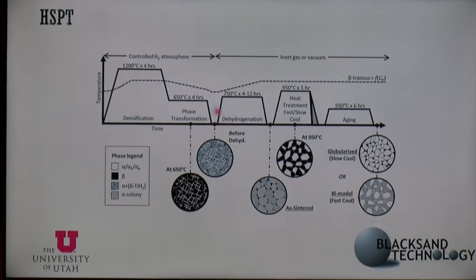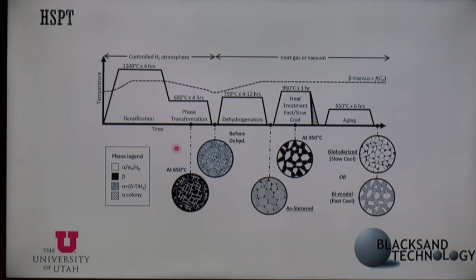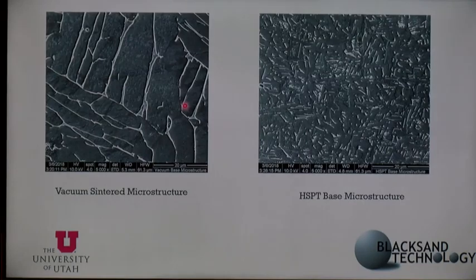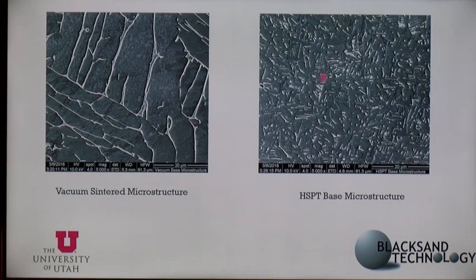You can see here that the left is the vacuum-sintered microstructure. This would be similar to what we would have at this point right here. So directly after this point, if we just completely stopped and didn't do anything with it, this would be a vacuum-sintered microstructure. By using that temperature, we control the grain size to go a lot smaller, essentially. And not to get too complex, but what happens is the material, instead of precipitating elements along the edges of the grains, precipitates the elements inside the grains. And that allows you to basically get a finer microstructure. We can control it at this point, but for our cases, the smaller the better. So you can see here on the left, you have a vacuum-sintered microstructure, and on the right, you have our base one. This is just to give you an idea of how fine it is.